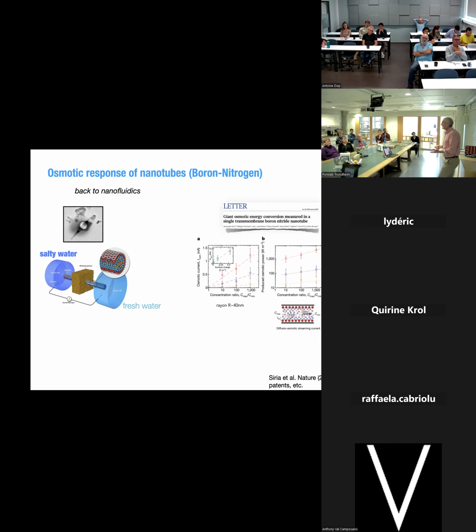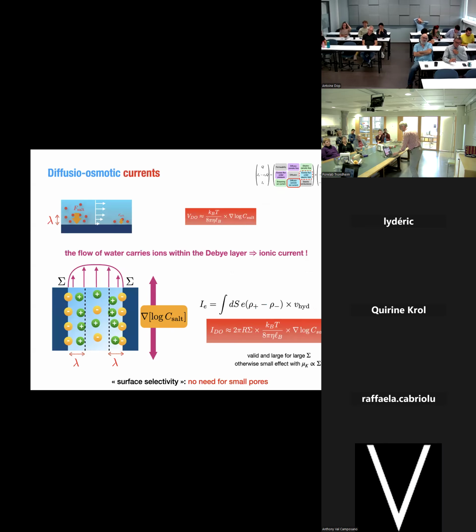And of course, if you remember what we discussed before, that's a question of diffusio-osmosis. As I was telling you before, if you have a gradient of solute, you can create a velocity. This velocity will carry the charge within the double layer, so you create an ionic current. This ionic current is simply, in some sense, this velocity times the surface charge, more or less. Actually, it's slightly more subtle than that if you do the proper calculation.